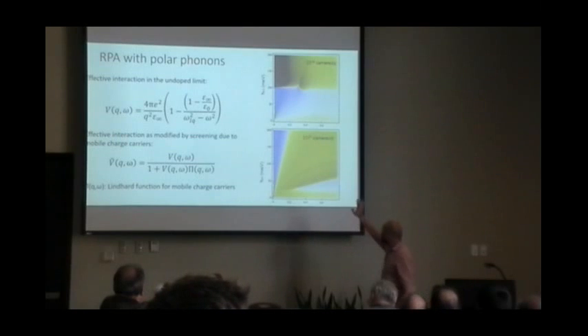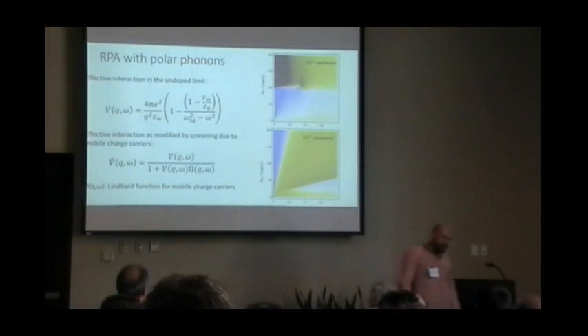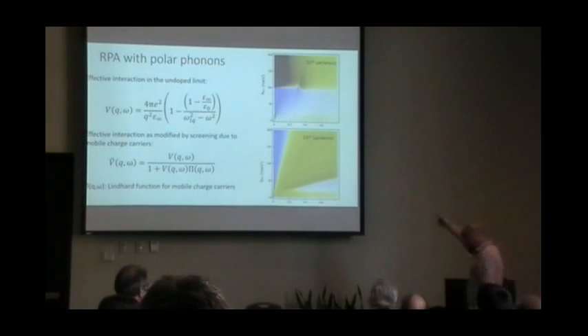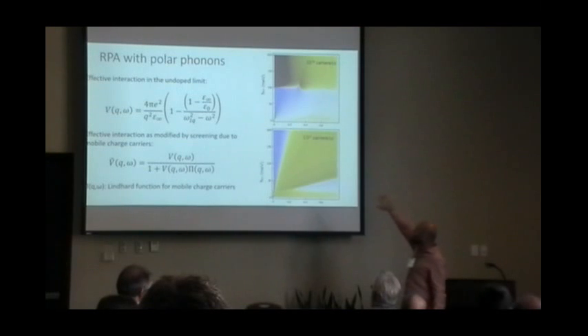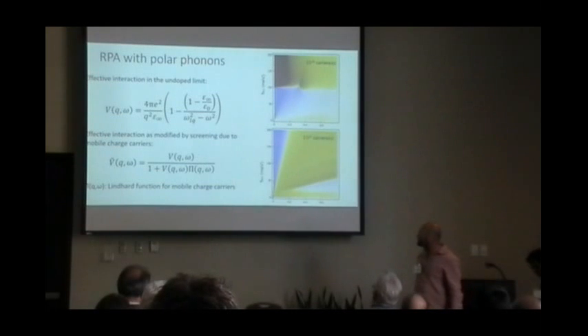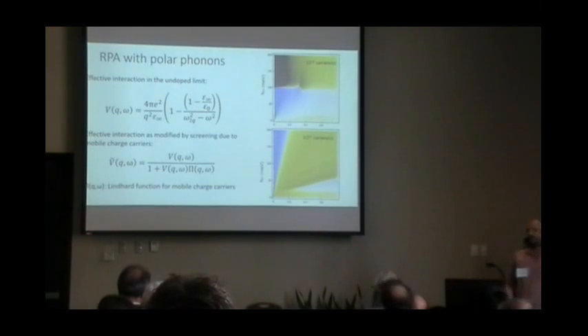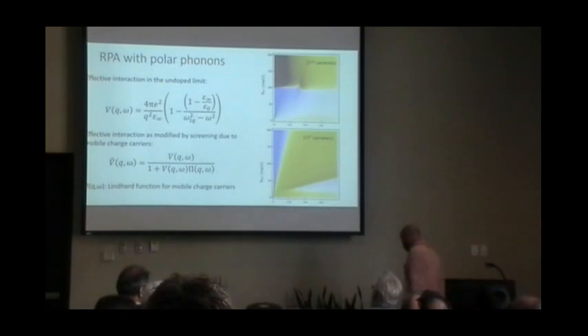And what you can see here now, if you put more electrons in the system, for the 10 to the 19 carriers, you find huge areas which are blue. Everything's a bit blue, but now huge areas of blue which are attractive. And the more electrons you put in, the more you will screen the polarization of the phonons, and what will happen is that you don't get the areas that are formally attractive.